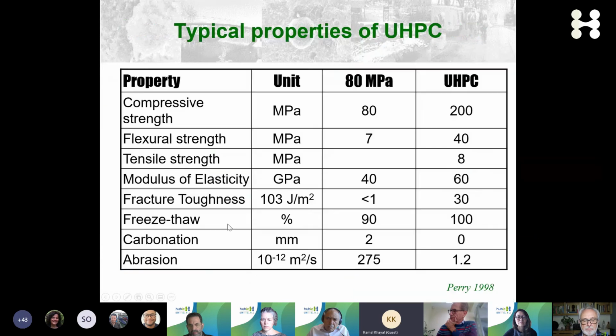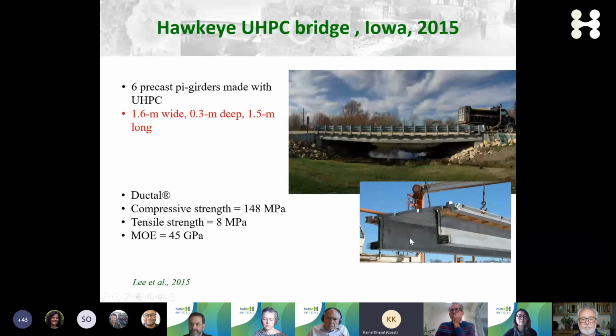So very elegant design. And if you compare mechanical properties of a UHPC versus high-strength concrete, you can see the flexure strength is very, very high. The elastic modulus also. And what's really important as we make transition to durability, this is an extremely durable material. So if you're trying to extend the service life, this is really a very good choice to consider. In the US, it has been penetrating the market quite a bit in the area of transportation infrastructure for the production of very high strengths, very high ductility and resilient structure elements, such as these bridge elements here.